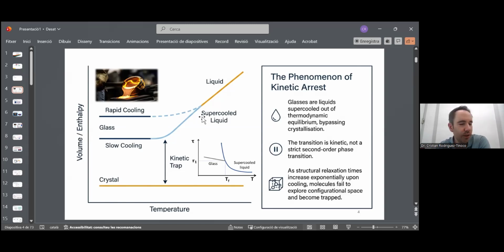So in any case, we will get a glass which deviates very soon from the liquid state at the glass transition temperature, which depends on the cooling rate, as I was saying, but you cannot get a broad range of glass transition temperatures by cooling at different rates, because of this abrupt increase in the relaxation time.